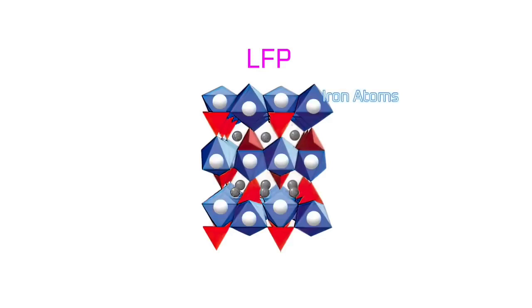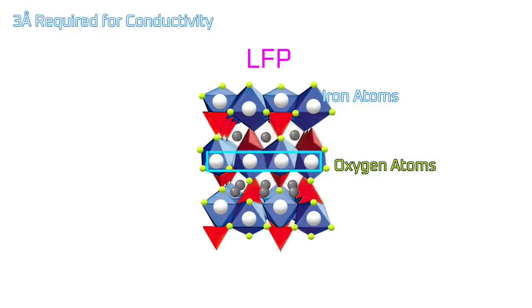In the center of each blue octahedron is an iron atom. There are oxygen atoms at each corner of the octahedron that put extra distance between the iron atoms. In order for iron to conduct electricity, each iron atom has to be within 3 angstroms of the next iron atom. The oxygen atoms at the corners of the blue octahedra force the iron atoms to 4 angstroms apart. An angstrom is just a measure of length at the atomic scale. The point is that the iron atoms can't conduct electricity with each other because they're spaced too far apart.